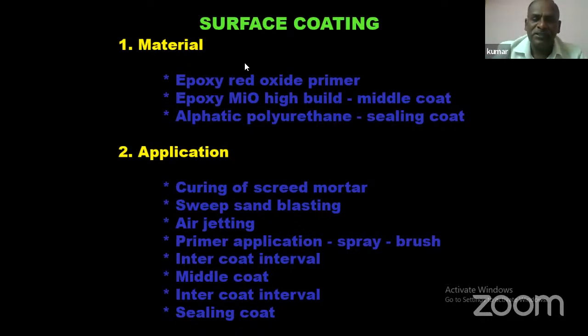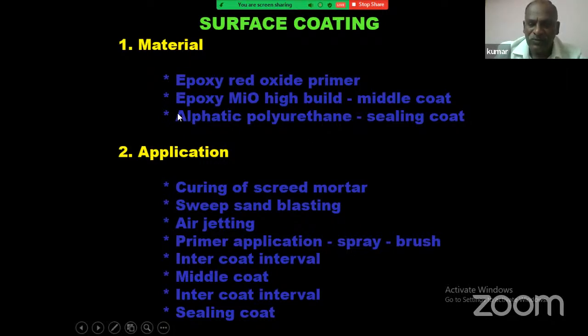So what are the materials? I'm highlighting epoxy red oxide primer on the surface, epoxy MIO high build middle coat, and aliphatic polyurethane sealing coat. Why do we have to give the aliphatic polyurethane sealing coat? Because the last one will not undergo ultraviolet degradation. In the sunlight, the ultraviolet will degrade the coating, any polymer. If you are using aliphatic polyurethane, that will not degrade your painting.